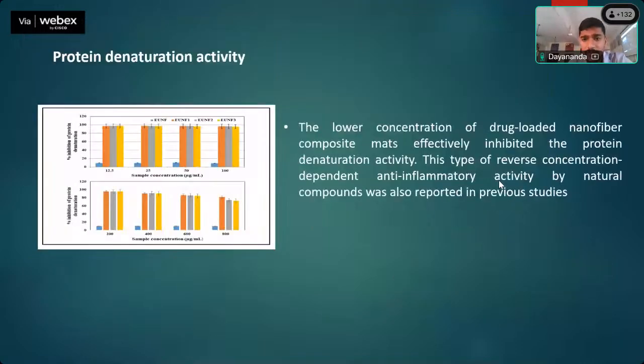Protein denaturation assay was also evaluated. From here it was found that reverse concentration-dependent anti-inflammatory activity was observed - the nanofiber mat with the lowest percentage of eugenol showed the highest activity. This is common in most natural drug release studies. The encapsulation efficiency of the nanofiber was 84% and 94%.